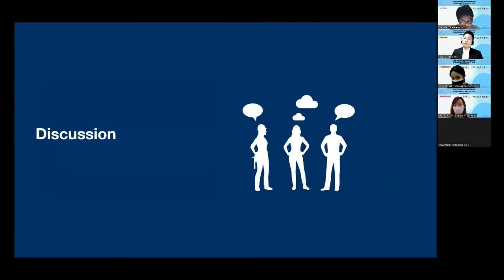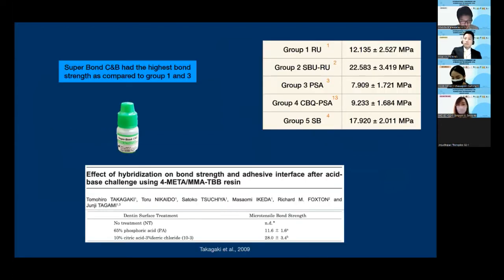Next is the discussion. The result of this study showed that Superbond had the highest bond strength as compared to non-universal adhesive treated groups. This could be due to the property of the ferric chloride in the green activator that can prevent the degradation of the collagen fiber at the decalcification layer. Takakaki et al. found that ferric ion absorbed dentin had a significant increase in bond strength to MMA resin, as reported in this study.